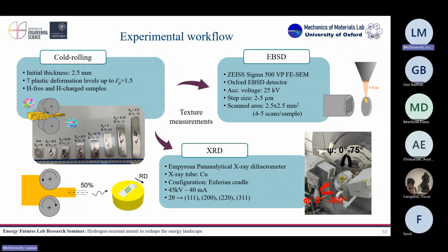With a tensile test, we can only go to maybe 10%, 15% of deformation before fracture. So we deformed the material a lot, up to an equivalent plastic strain of 1.5. Compared to tensile, where you can maybe get 0.1, it's a lot. And we measure the texture using different methods. So we use EBSD and then we use XRD.